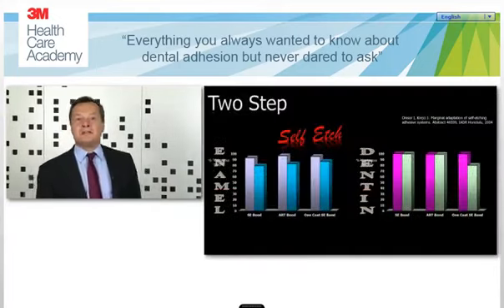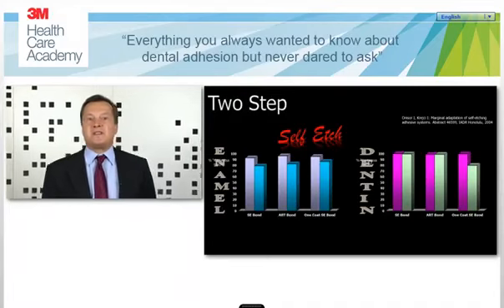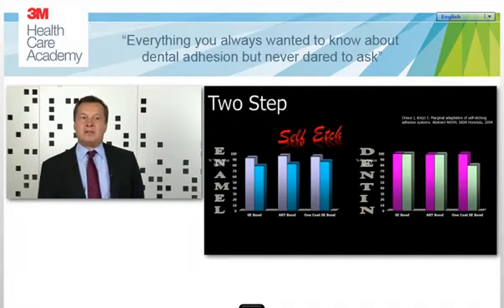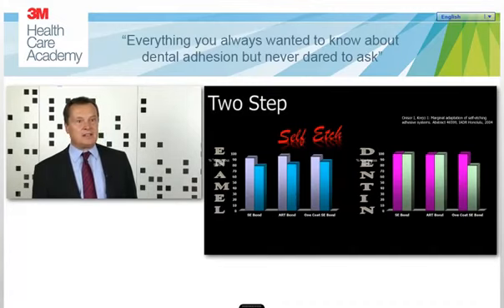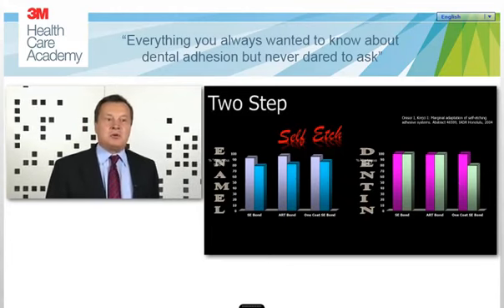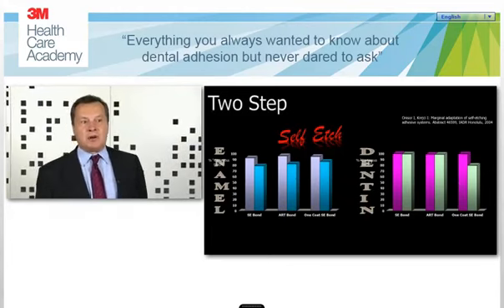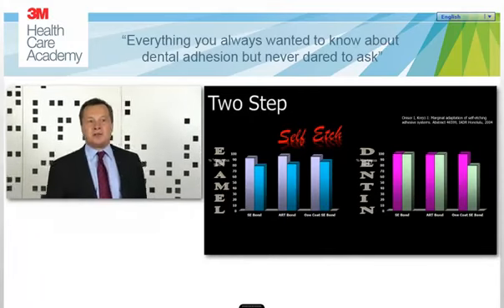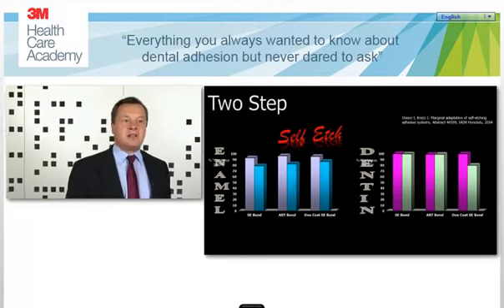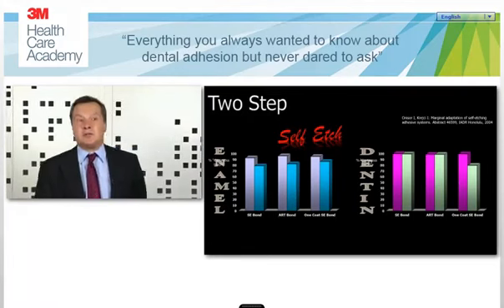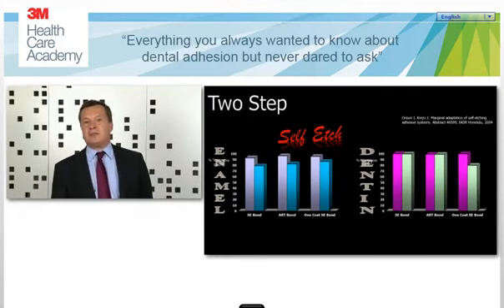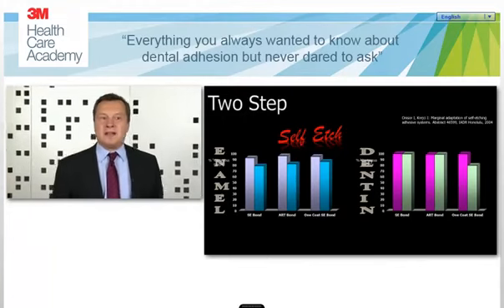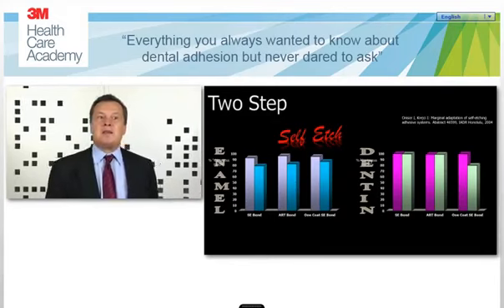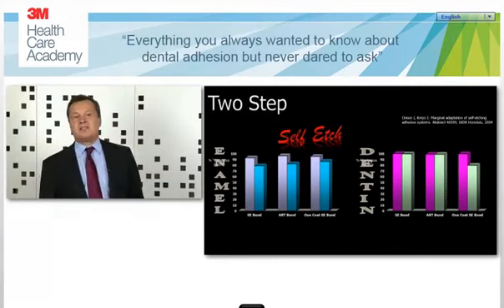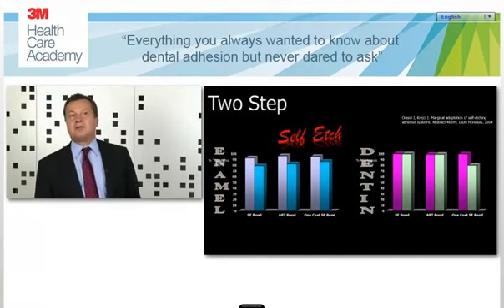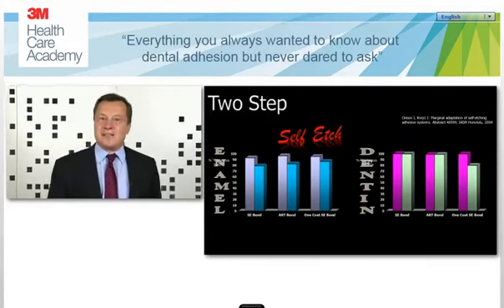Now, what is interesting is to compare this gold standard, three-step etch and rinse gold standard, with some simplified systems. And as I already told you, we have an enormous amount of data on many, many different adhesive systems. But just to give you an example, what you can see here is the marginal adaptation of SE Bond from Kuraray in enamel and in dentin, always on the left of these two graphs. And you can see that we have a marginal adaptation in respect to percentage of continuous margins of about 90% before loading and maybe about 75% after loading, which corresponds pretty well to Optibond FL. And on dentin, this already simplified system, before loading is at about 95% of continuous margins, and after loading also at about 95% of continuous margins. So at least as good as the gold standard.